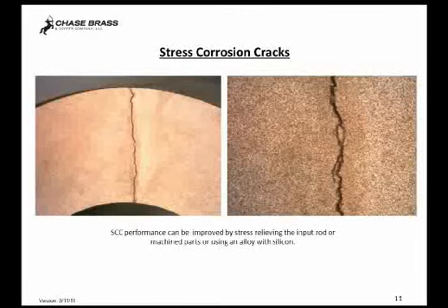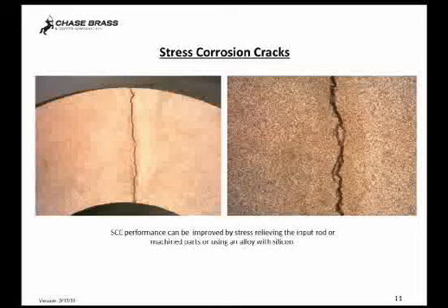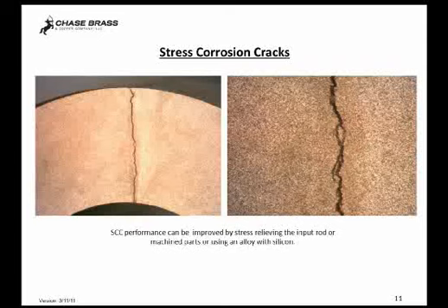Under a microscope, stress corrosion cracking looks like this. It kind of looks like a lightning strike through the brass. As we mentioned, that's caused by a combination of high levels of stress, either from the production of the input material, the production of the part, or the installation of the part, and then exposure to something that attacks the grain boundaries of the brass. Typically, it's ammonia. Mercury will also attack it, but that's not typically found in your standard home environment. NSF 14 requires that materials that are used for PEX fittings have the kind of alloy composition that resists both forms, either stress corrosion cracking or dezincification resistance, just as a summary.